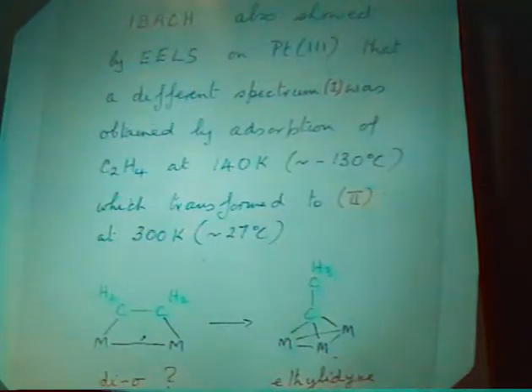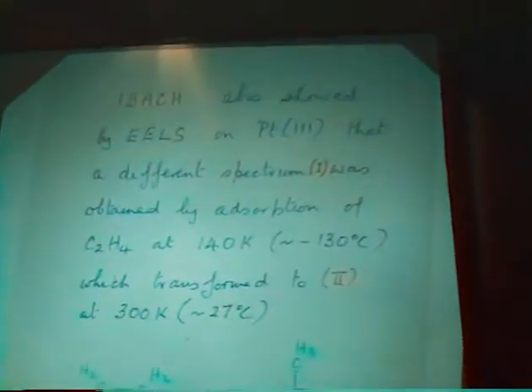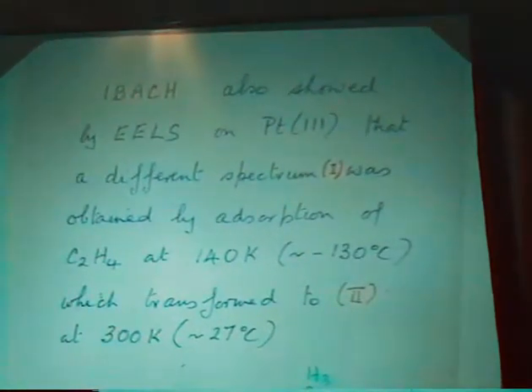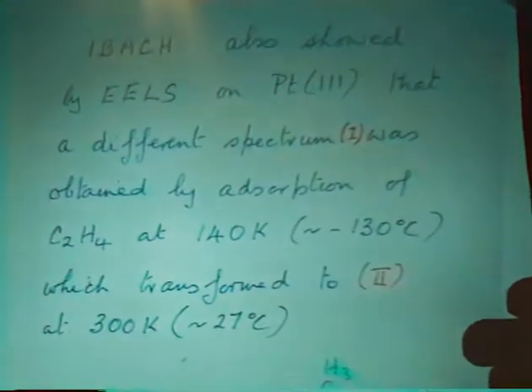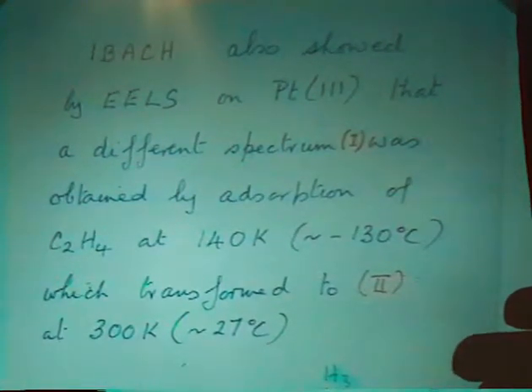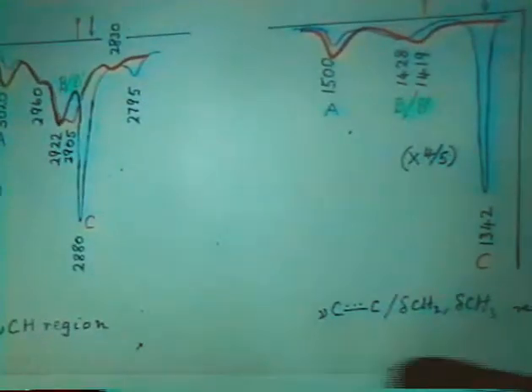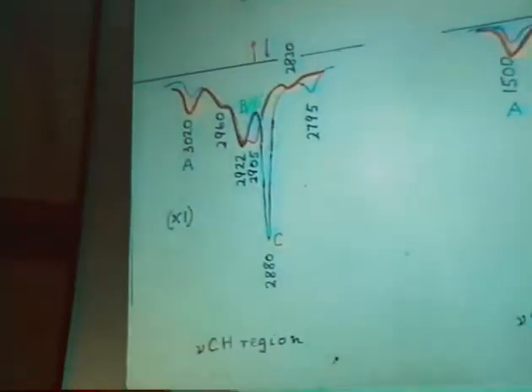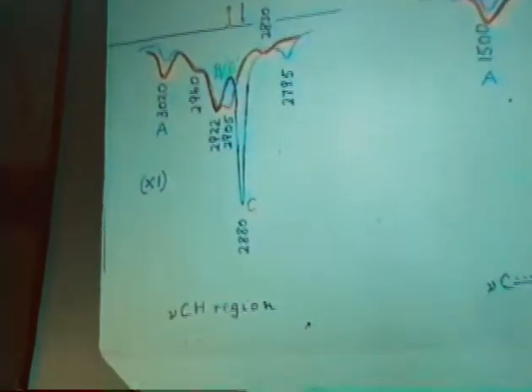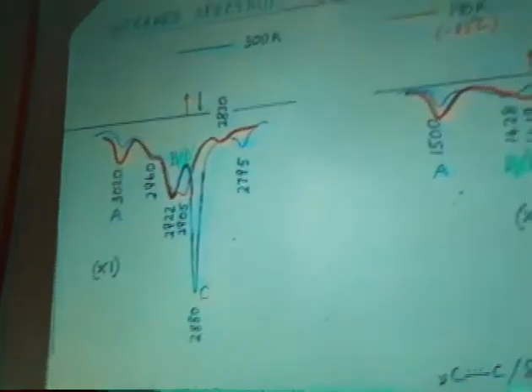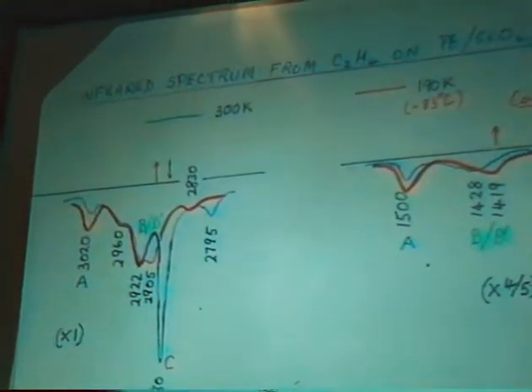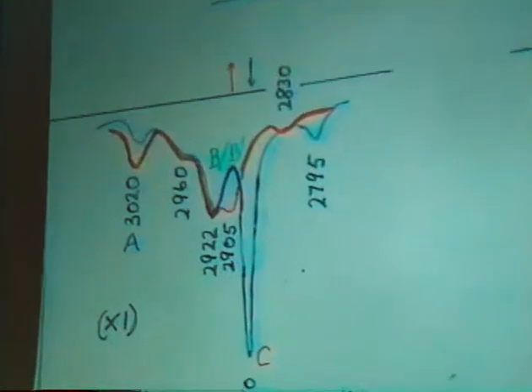I mentioned that Ibach had shown that at room temperature the spectrum, which we identified as ethylidyne, and a different spectrum at low temperature. It happened to be the di-sigma species. So we went back to our own spectra on the finely divided catalyst to redo the low temperature experiment that had originally been done, but with better resolution from FTIR. Carlos de la Cruz was the student who did this.